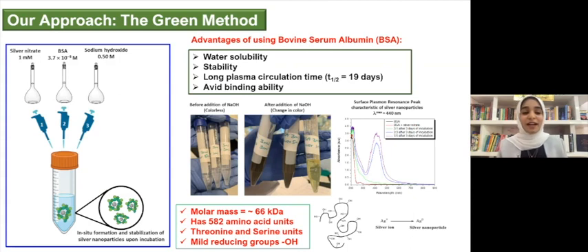So on the left-hand side, you can see a schematic of our procedure. So we added 1 millimolar of silver nitrate and 3.7 times 10 to the minus 5 of BSA. We shook the tube for 10 seconds, and then we added half molar of sodium hydroxide. And then we observed the first indication we got, which was a very distinctive color change. So in the images in the center of the slide, you'll see we have 3 tubes, which are colorless solutions, and then next to that, they're very distinct colors.